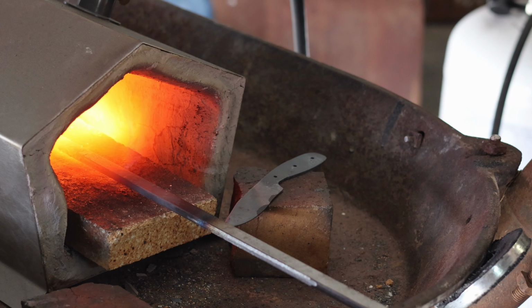The goal is to get to the point where the steel is no longer magnetic, and then a little bit hotter, and then I will quench in a preheated mineral oil. While mineral oil isn't the best, I had a gallon of mineral oil hanging around from forever ago and decided I was going to use it for this knife since it's close to Parks 50. It's a little more of a medium quenchant as opposed to a fast, but it should do the trick and give me a decent hardness on this blade.